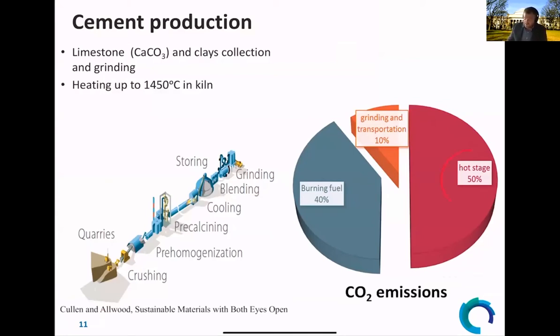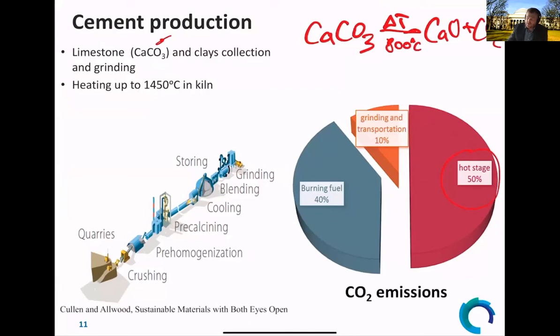Half, basically, of the CO2 emission comes from the degradation of the main ingredient necessary to make our cement clinker, and this is calcium carbonate. So if you take calcium carbonate and bake it at about 800 degrees C, you will produce calcium oxide plus CO2, and this CO2 is a gas, and this accounts for 50% of the CO2. And the other part is definitely burning fuel. Most of the fuels we burn indeed produce CO2 and water, and so that's a problem.